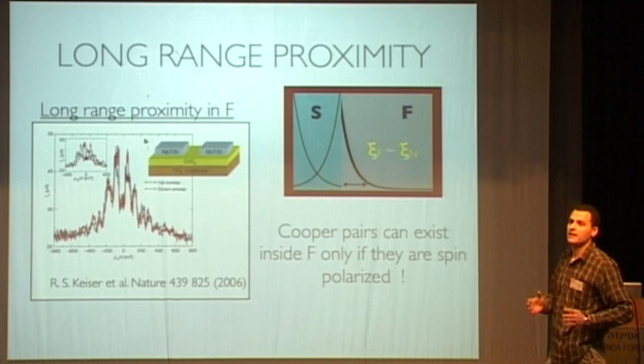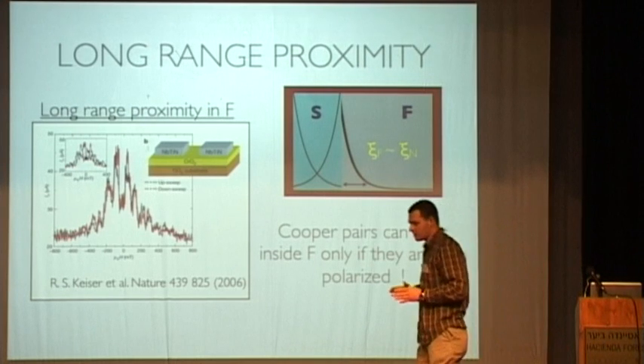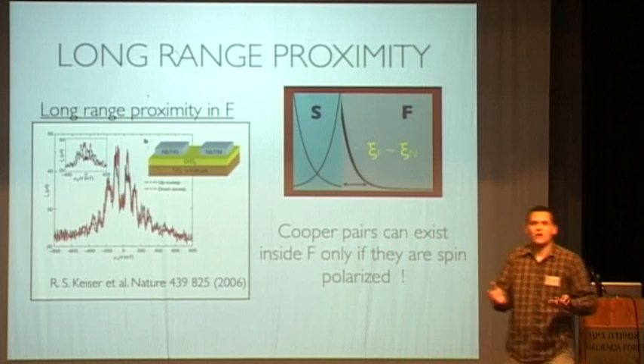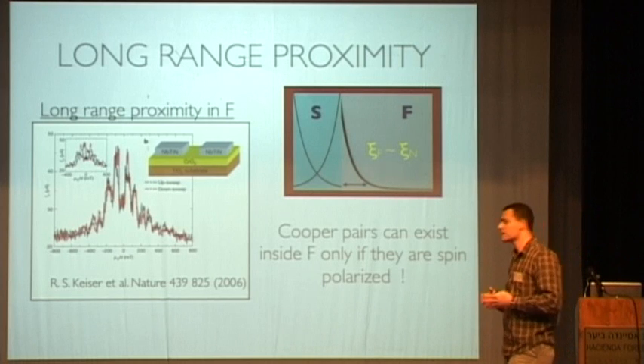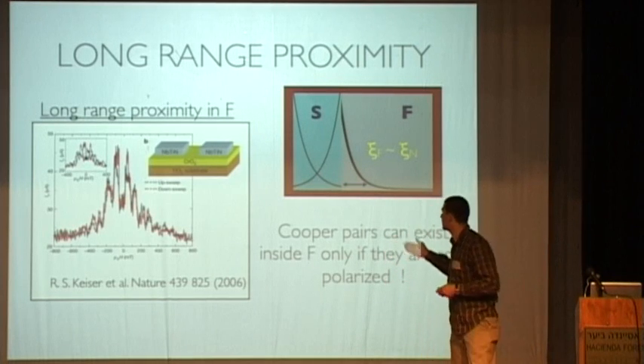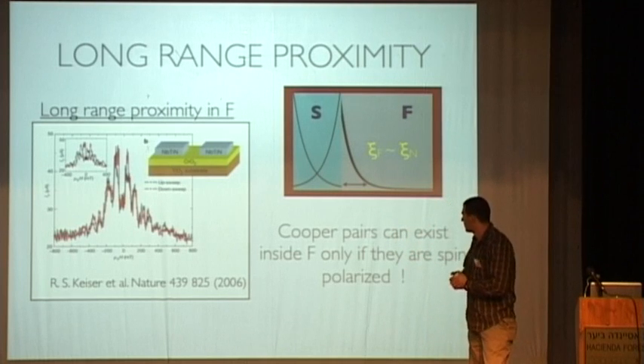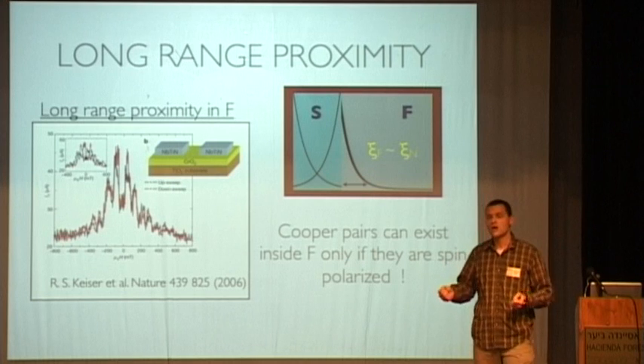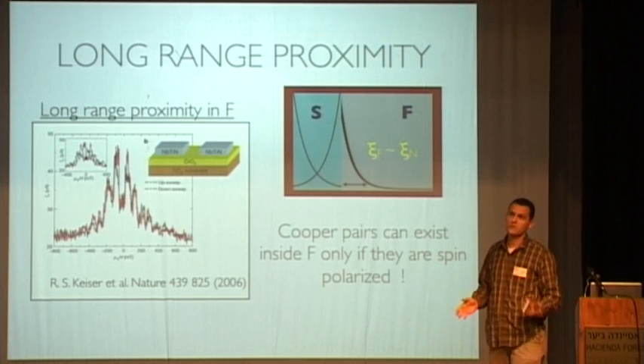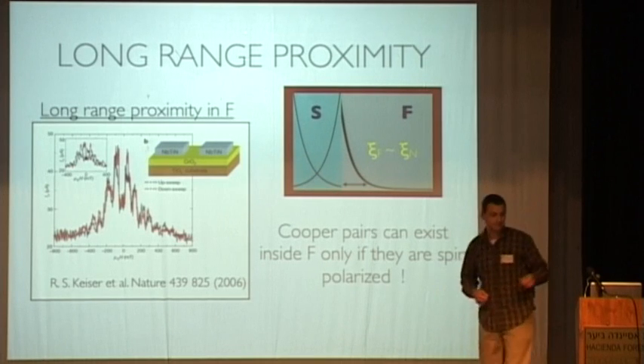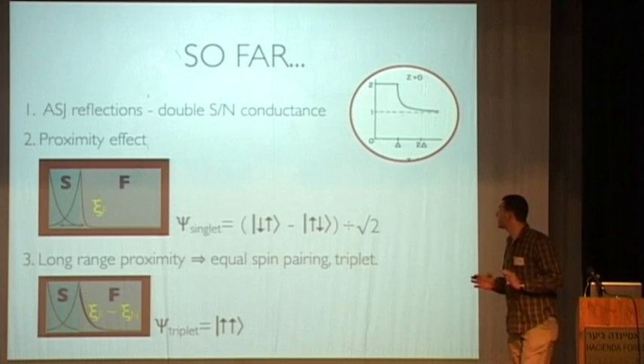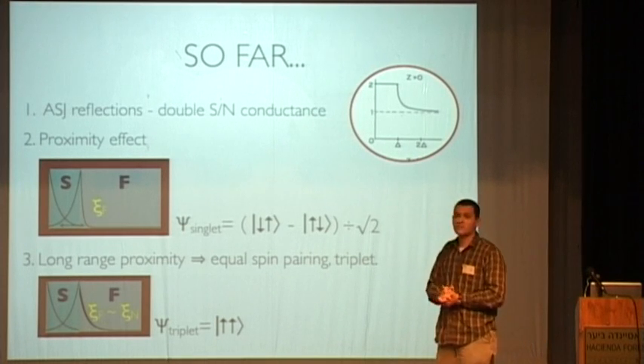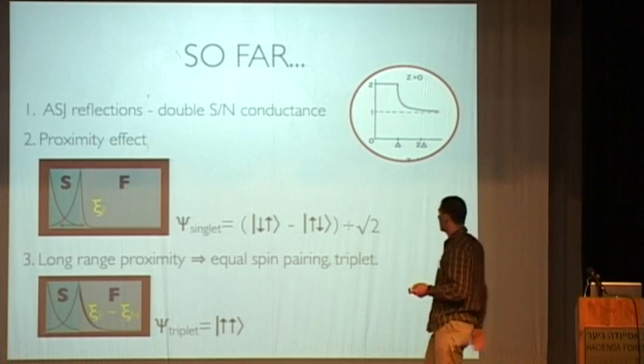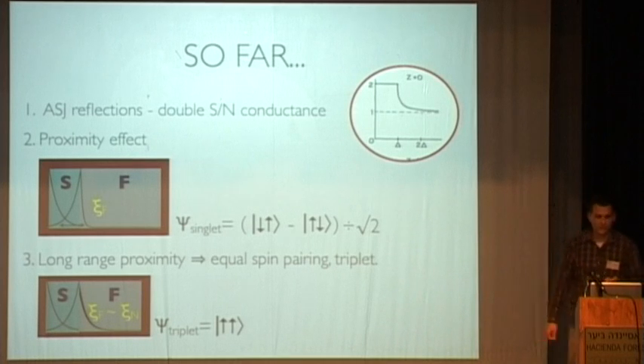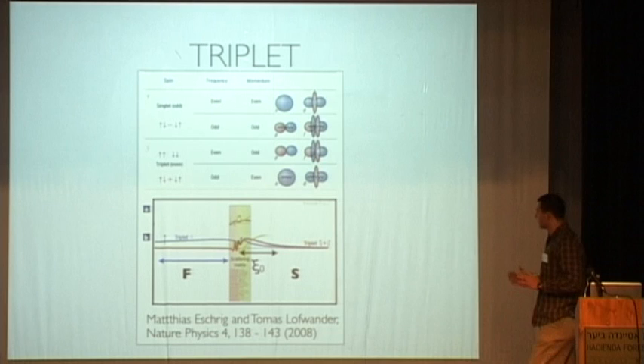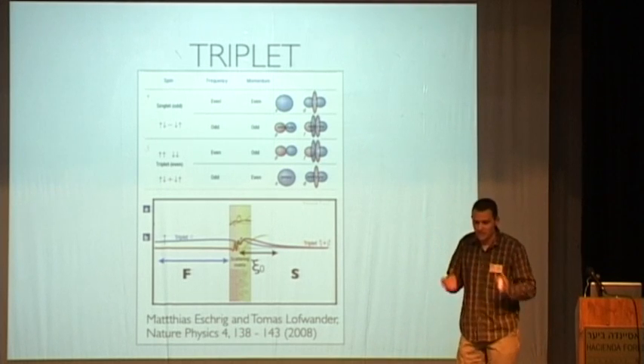Now, if we look at the triplet superconductivity, because the Cooper pairs are polarized, they don't care about the magnetic field. They can penetrate long distances into the ferromagnet. And this fact was verified in an experiment. Here in a very nice example, published in Nature, they measured supercurrent long distances into the ferromagnet, which can only be true if we have triplet pairing, equal spins. Now, so far I introduced you to Andreev reflection, the normal proximity effect, and the long-range proximity effect due to the equal spins in the superconductor. Now, as I mentioned, the long-range penetration inside the ferromagnet was measured and is known.